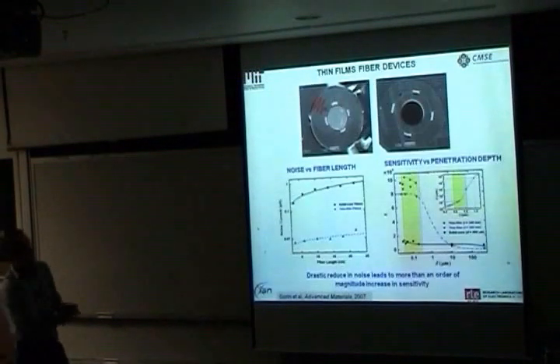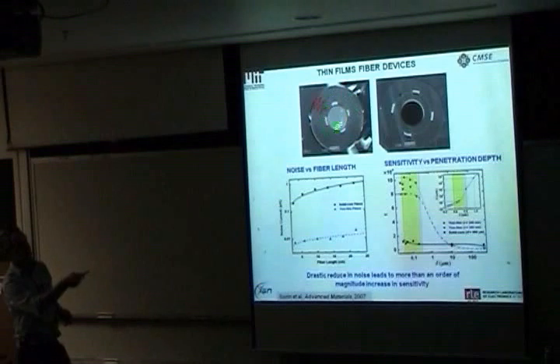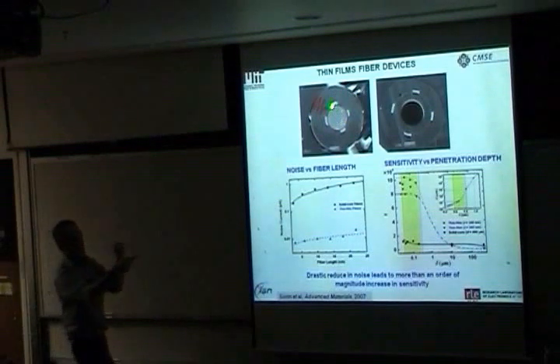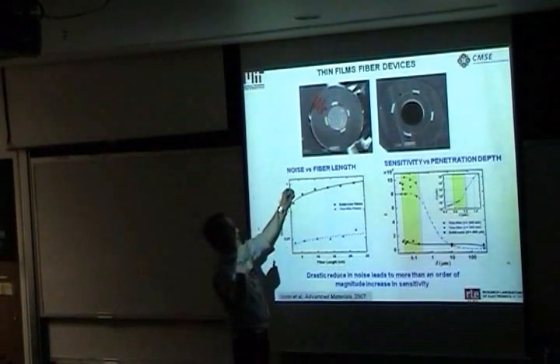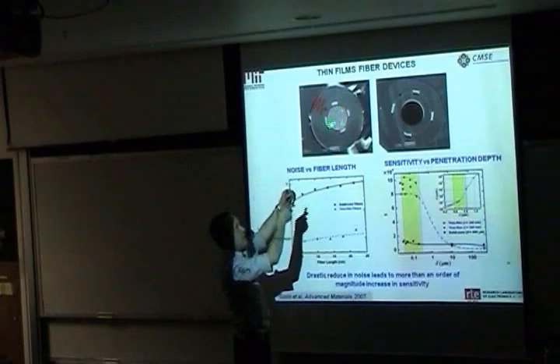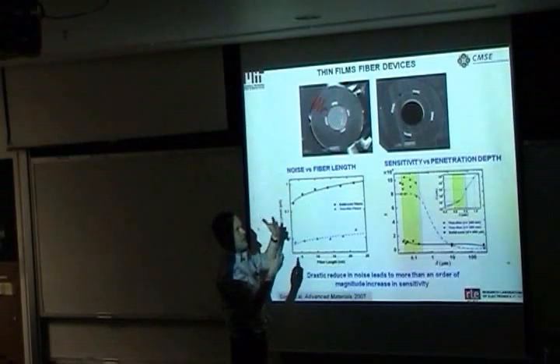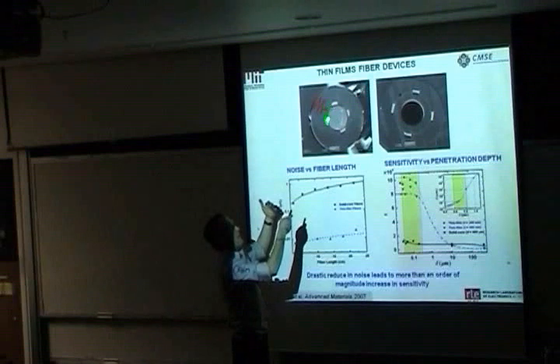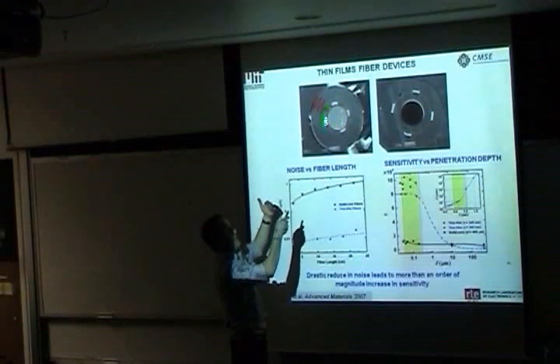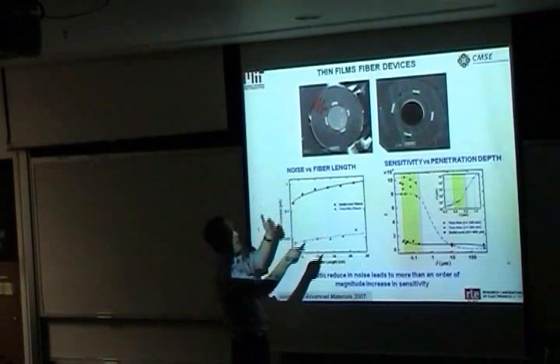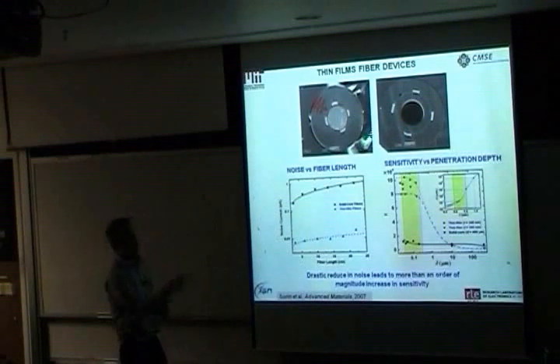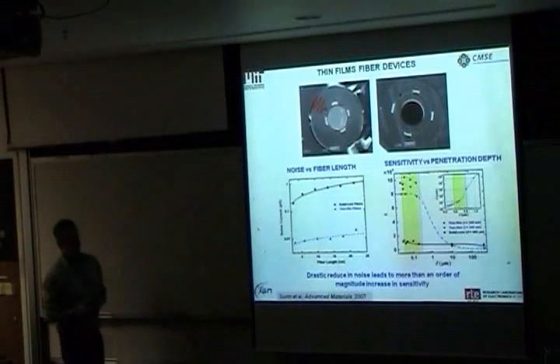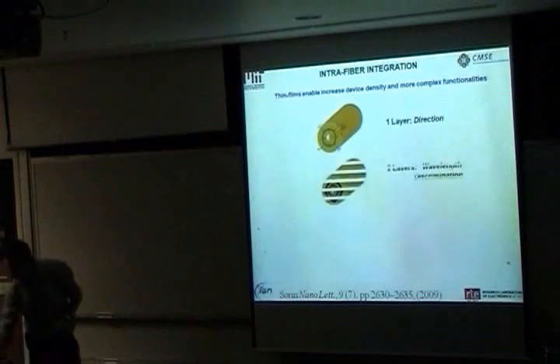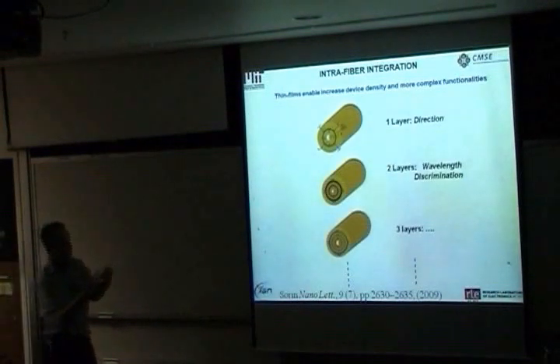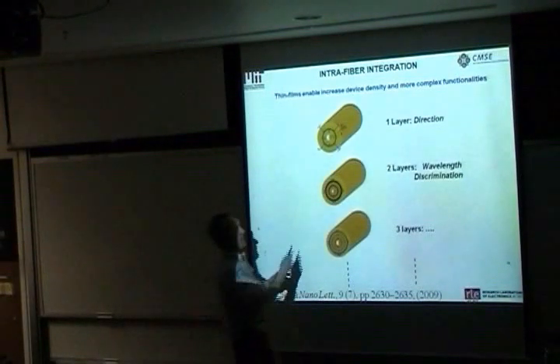Now, all of this was initially based on the detectors that I just mentioned to you, which were bulk detectors. There's a bulk semiconductor running through the entire core of the fiber contacted by these metals. But then we realized that, in fact, light penetrates to a very shallow extent into the semiconductor, and we would be better off from a standpoint of signal to noise to just going to a very thin semiconductor shell. And that allowed us to come up with a concept of these nested detector shells.